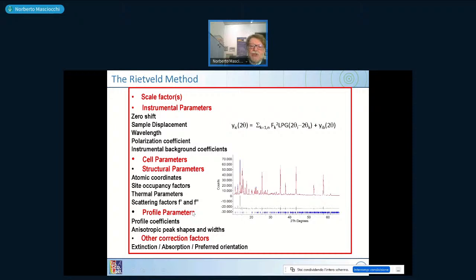You have profile parameters, the shape of the profile, which you cannot eliminate. You have the anisotropic peak shape and width, that means some peaks are narrow, some peaks are broader, and then other correction factors. So this is a list of parameters which can easily be more than 50 parameters. That means you have to find the minimum of one function, the best agreement, searching and spanning a hyperspace of 51 parameters: 50 independent parameters, and the one is your best matching. This is a very formidable task and can be done nowadays by powerful computers.